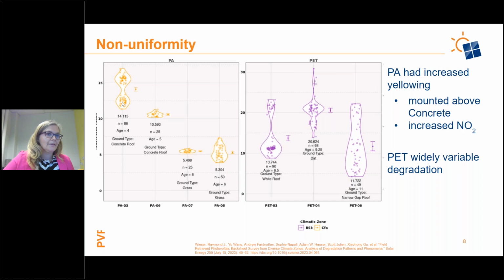So what you're seeing here is that there are differences of degradation over the whole back of that module. So we have a spatial degradation over this particular one. You see very varied degradation. These are mounted on concrete roofs. These two were mounted on grass in the same climate zone with longer years of exposure. So we definitely have a difference in temperature or potentially albedo. These two on concrete roofs also potentially had a higher pollution content, so there was higher NOx there, which we know attacks polyamide. So that's something to consider: pollution in the air can also attack these polymers.